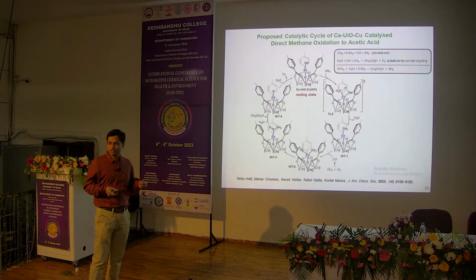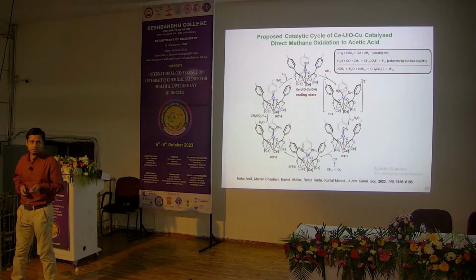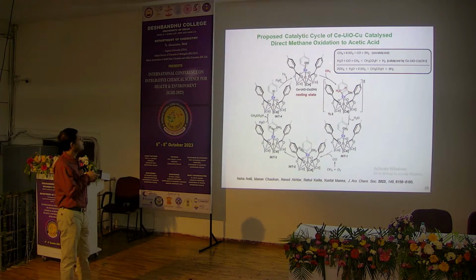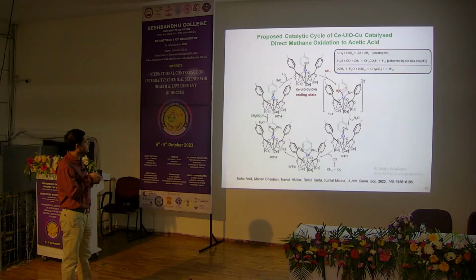And in the XAS analysis, we found that the structure of the species is the copper hydroxyl species. So based on this experimental data, we propose that the first step is methane activation, where methane is activated with copper hydroxyl via sigma bond metathesis to get the copper methyl species. Then CO coordinates, and CO is formed by the oxidation of methane and oxygen, that is, in situ formation of CO.